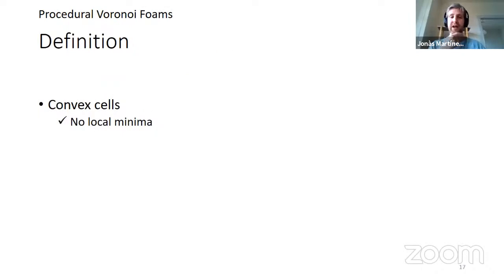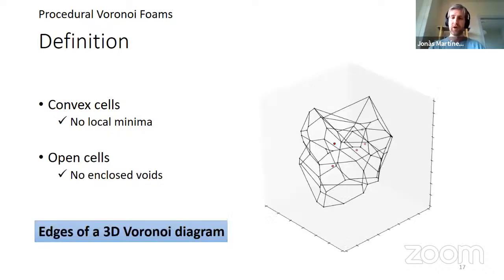So we figured out that having a cellular structure with convex cells is good, because then you guarantee that you don't have local minima. And in particular, an open cell structure doesn't have enclosed voids. So just taking the edges of a 3D Voronoi diagram seemed promising.